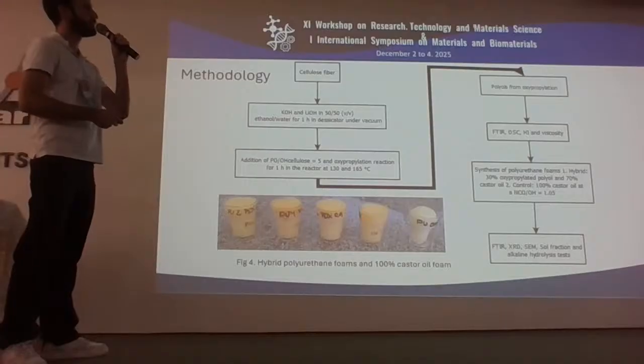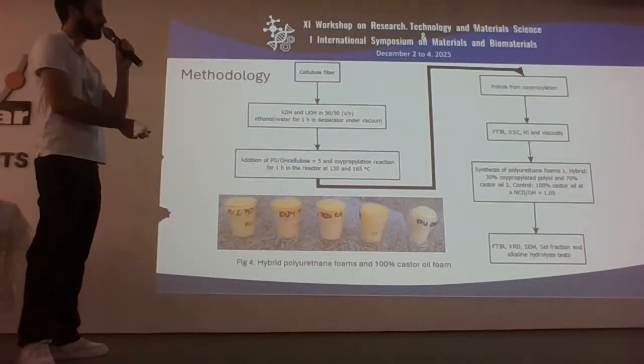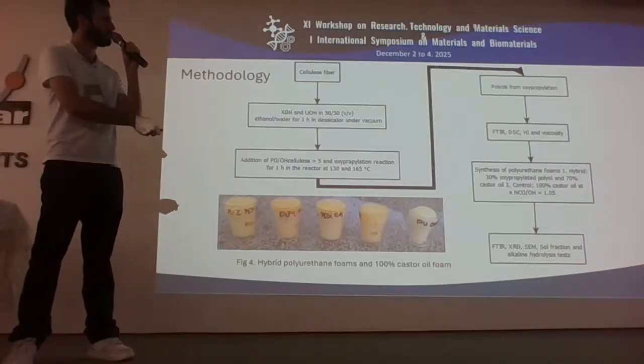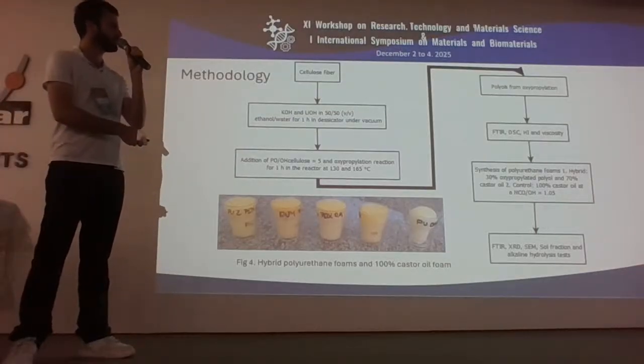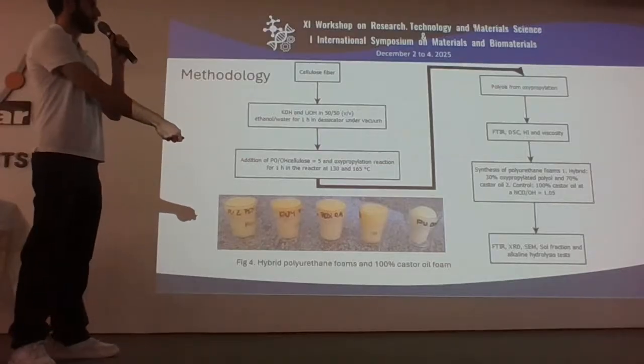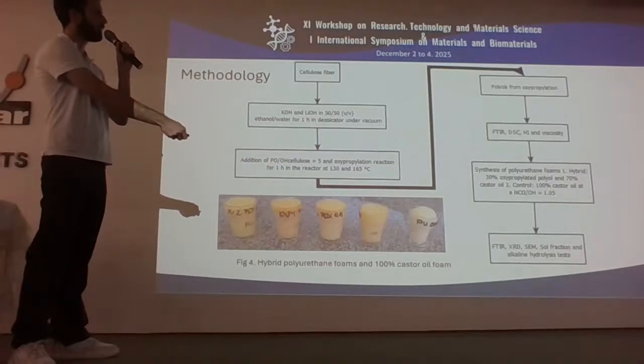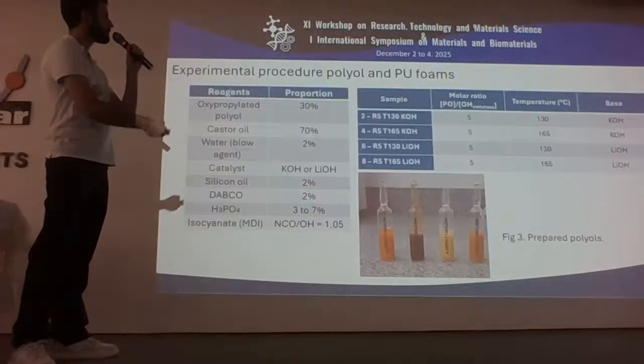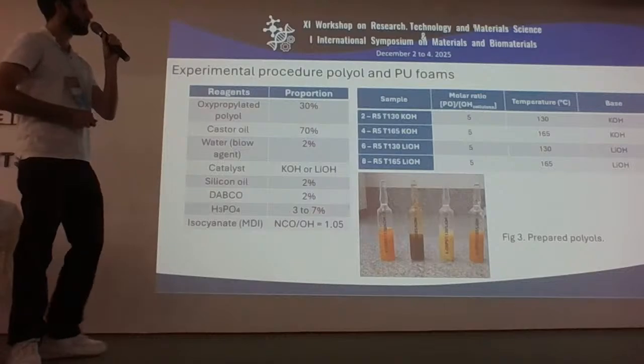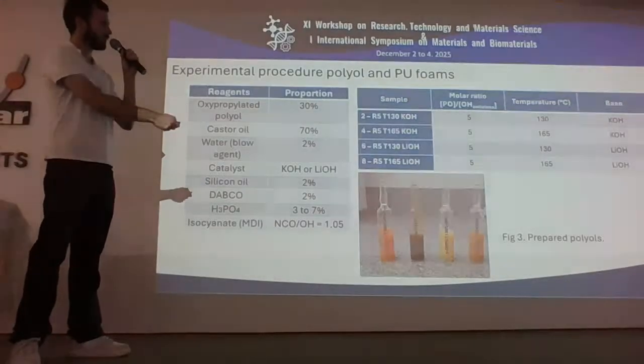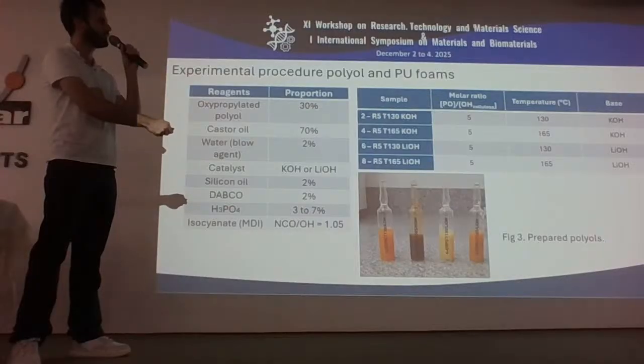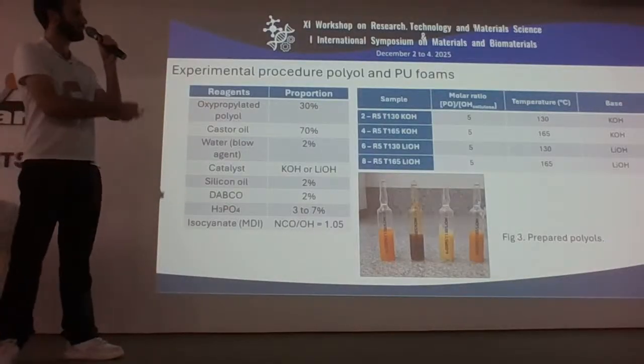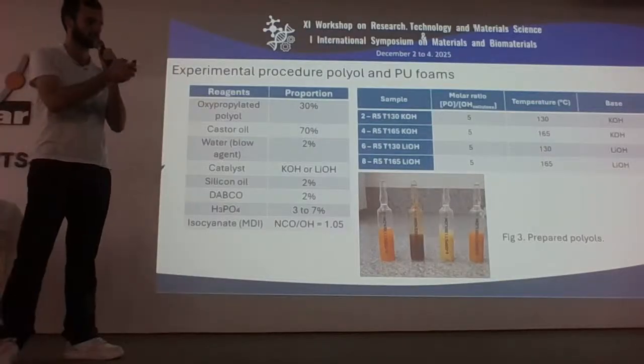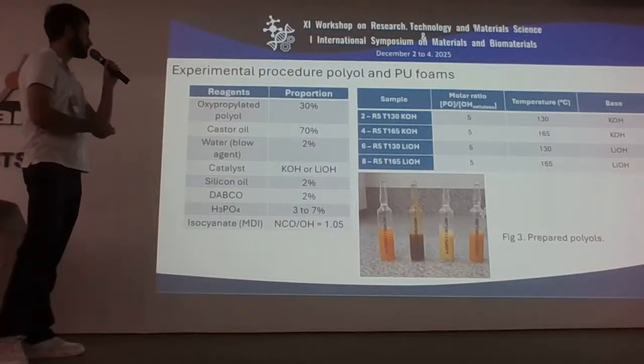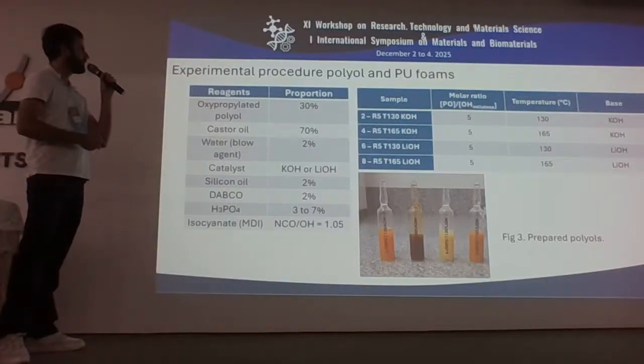So after obtaining the polyols from the oxypropylation, we synthesized a control foam with 100% castor oil, and a modified foam with a slight excess of isocyanate. It was characterized by FTIR, XRD, SEM, sol fraction, and alkaline hydrolysis tests. So we obtained basically 4 different types of polyols in the reactor at temperatures of 130 and 165 degrees Celsius, and the catalyst bases used were potassium hydroxide and lithium hydroxide. For the polyurethane foam synthesis, we used 30% of the oxypropylated polyol and 70% of castor oil, with a slight excess of isocyanate.